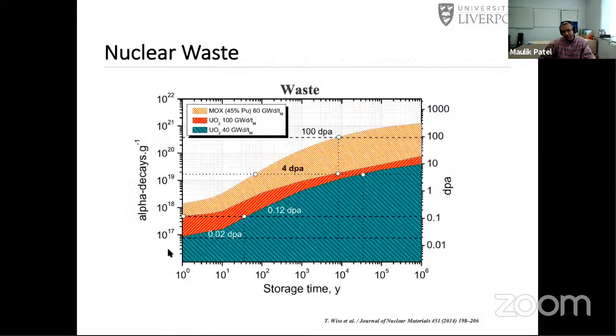This waste is going to be there forever. And the number of displacements per atom, let's say in this case it's a MOX fuel, is enormous. When I say 1 dpa, it means that if you have a material that is irradiated, all the atoms in, let's say, a cube of material are displaced at least once. Now, if you go to high alpha activity over maybe 10,000 years, you have at least 100 dpa, which means that each atom has been displaced 100 times. And you can imagine what that would do to the properties of the waste matrices.